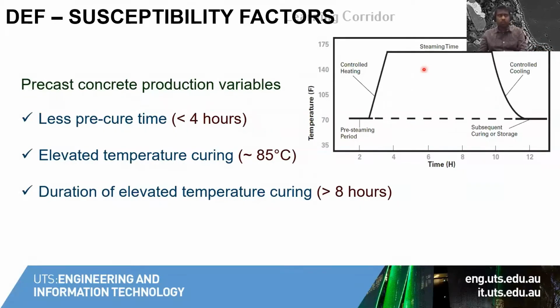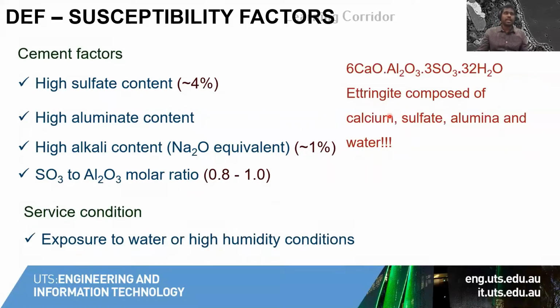in the long run. And then cement factors, as I already mentioned, ettringite is calcium aluminosulfate hydrate, which is composed of calcium, sulfate, alumina, and lots of water. So anything related to alumina and the sulfur content is going to impact the quantity. The quantity basically depends on how much aluminates and sulfates are present in the cement. So we don't consider calcium, because calcium is always supersaturated in cementitious systems. So basically the quantity of ettringite precipitating in the system depends on alumina and sulfates in the system.